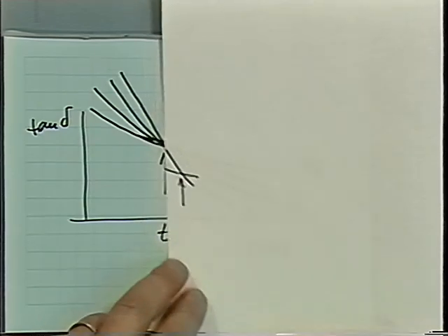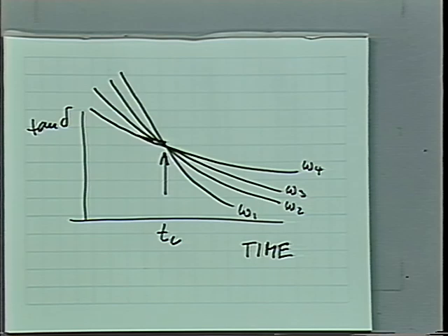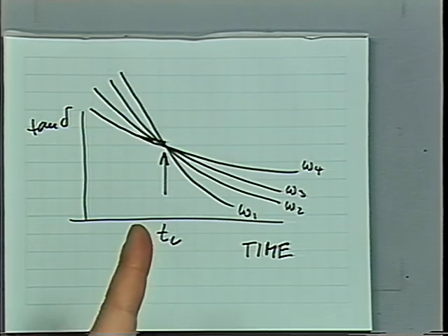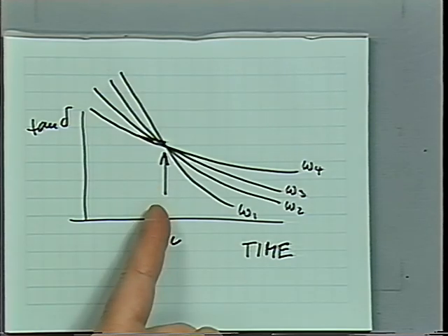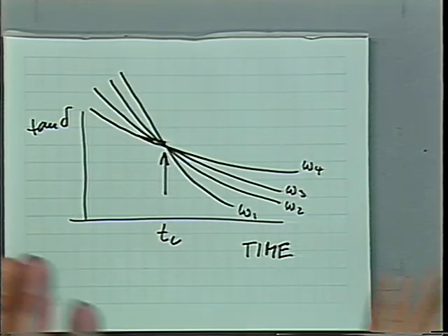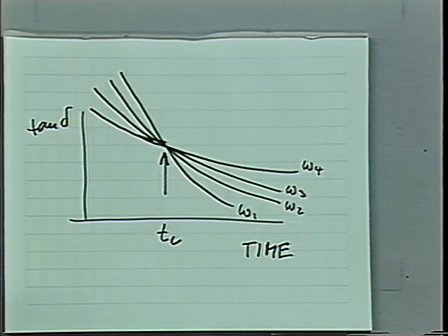That has been used for making toner materials, which should be close to the gel point, should be highly cross-linked, but should never solidify. Okay? So it's a very powerful method, and it is the first method and the only method I know which gives the gel point directly. All other methods are extrapolation methods, and the results from this technique agree with the other techniques.